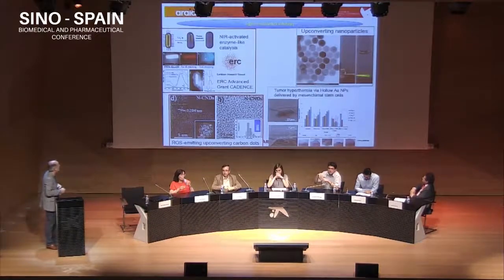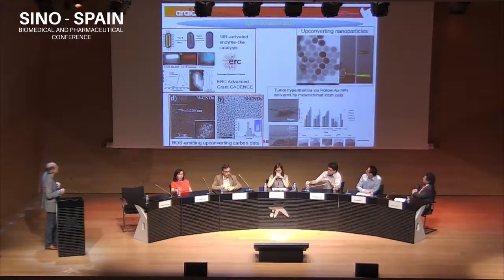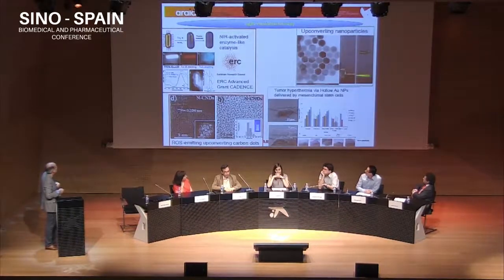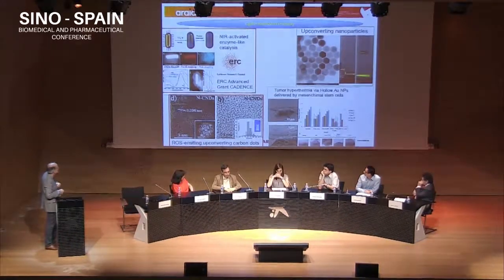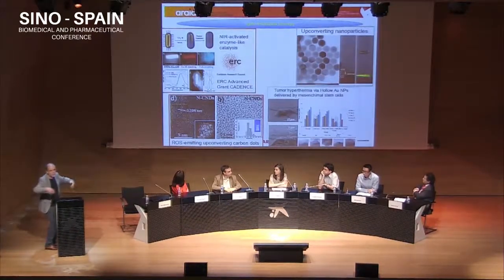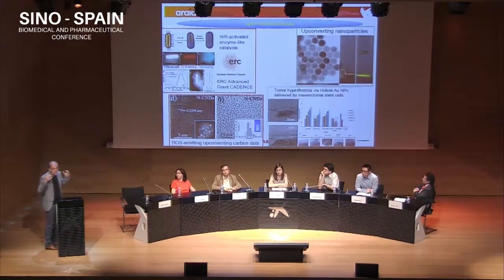And finally, we also have nanoparticles that behave like enzymes. So we call them enzyme-like catalysts. This is a gold nanorod that we have surrounded with a titanium coating, okay? So the idea is that the gold nanorod is able to harvest light of around 800 nanometers, as you see here, and it excites the electrons, creating what is called a plasmon resonance, which is a collective oscillation of electrons in the gold nanorod.